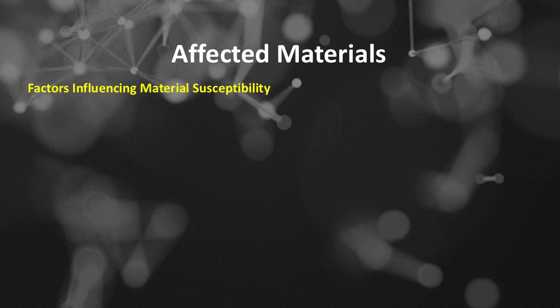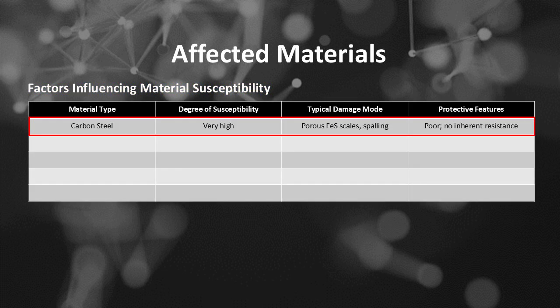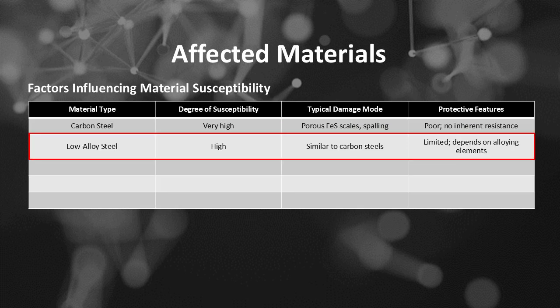Factors influencing material susceptibility. If material type is carbon steel, then degree of susceptibility is very high, then its typical damage mode is porous FeS scales, spalling, then its protective features is poor, no inherent resistance. If material type is low alloy steel, then its degree of susceptibility is high, then its typical damage mode is similar to carbon steels, then its protective features is limited, depends on alloying elements.